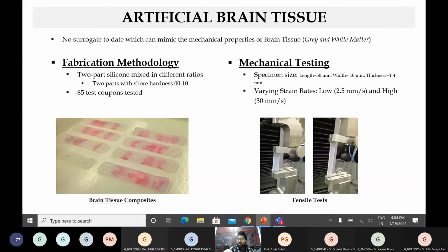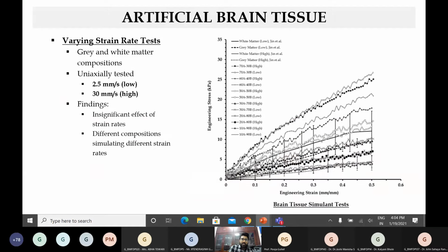So we looked at varying strain rates for developing these tissues and went all the way from 2.5 millimeters per second to 30 millimeters per second. These are all displacement rates, by the way. And this is a tensile testing specimen. So these are some of the results, just the key highlights.